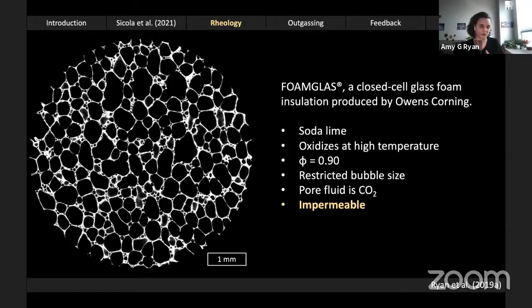In contrast to Stefania's experiments or previous experiments that have been conducted where the pore fluid is water, here it's CO2. That's notable because the solubilities of those two volatile phases are quite different. Water has the potential to resorb back into the melt or to diffuse out of the system, whereas the low solubility of CO2 means it's sort of trapped in space. The last really cool feature of foam glass is that it's initially impermeable, despite its very, very high porosity.